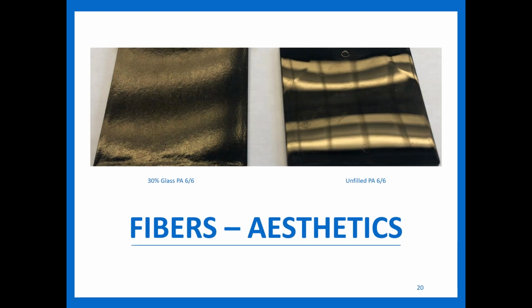So the next thing I want to talk about is aesthetics. Glass at this point is sounding pretty good. You get a good boost in mechanicals, you get a good boost in thermal. We are warning about the shrinkage difference, but as long as you design for that and you're prepared for that, everything sounds great. You're like, this is wonderful, I'm getting everything I need out of this. The other thing to keep in mind is glass will end up on the surface. It will make the surface a little bit rougher and it will affect the appearance of the material. If you look at this part on the left-hand side, this is a 30% glass PA66 grade. You can see it's a little bit rougher, not as shiny, not as glossy compared to your unfilled 6.6. So you are going to see a difference in the way that it looks.